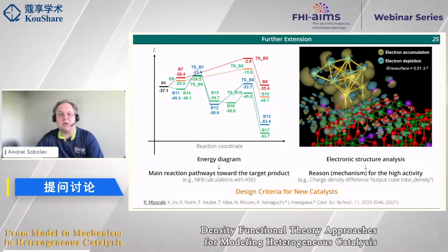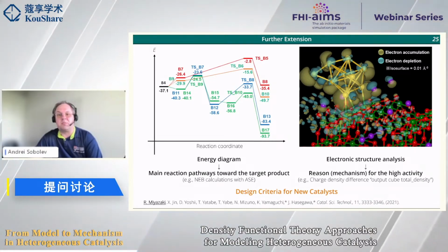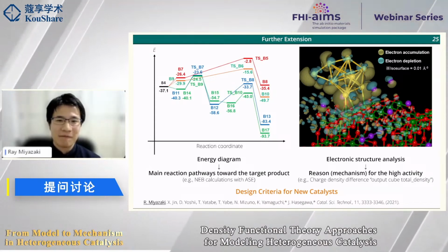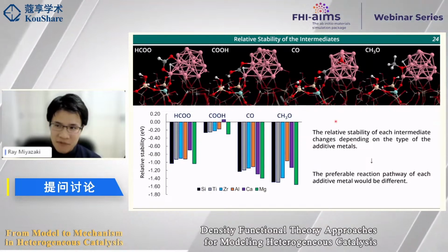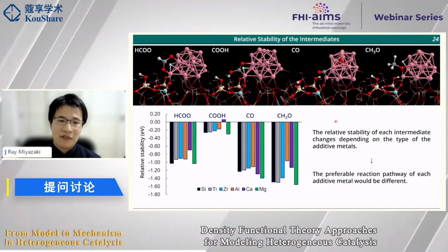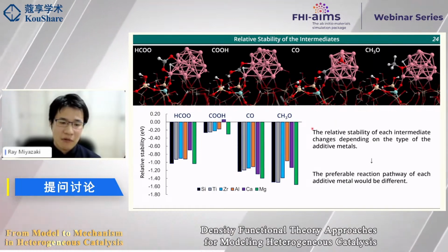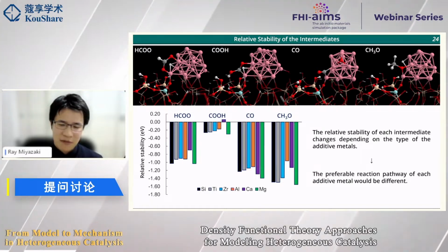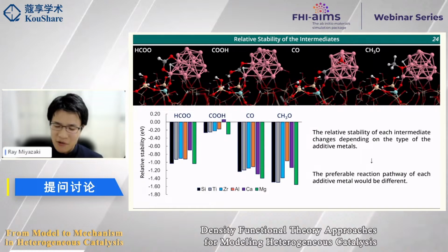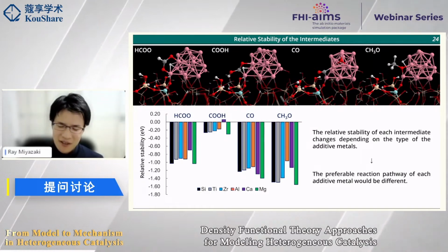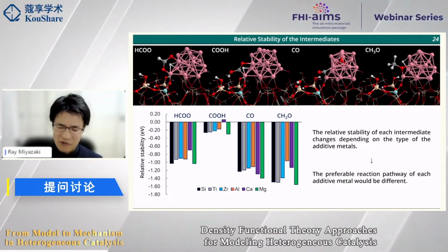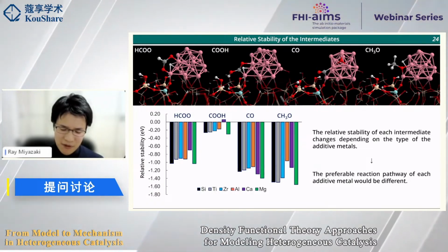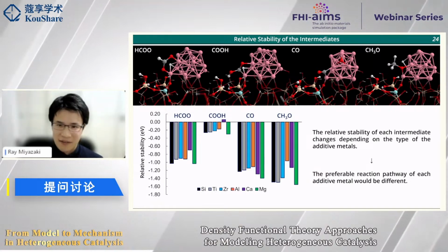There is one more question from Oscar. Is this something that your experimental collaborators could probe? Actually, that is also a very nice question. That is unknown. Even now, it is a very unknown part for me. My experimental collaborator mentioned that, particularly for the titanium case, they investigated this kind of species, or aluminum. Those species are randomly dispersed in the silica, which means atomic dispersion. But for titanium, they found that of course there is some kind of atomic site of the titanium, but they also found an island structure of titanium oxide at the interface.